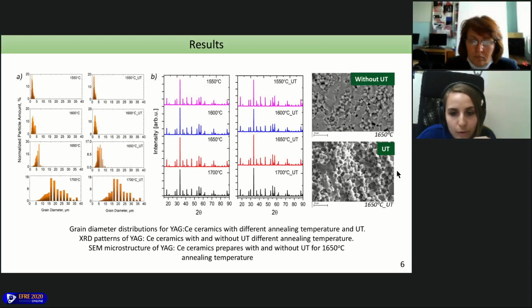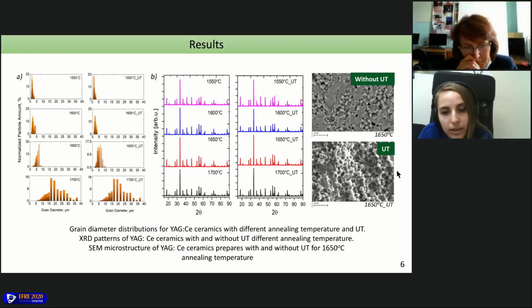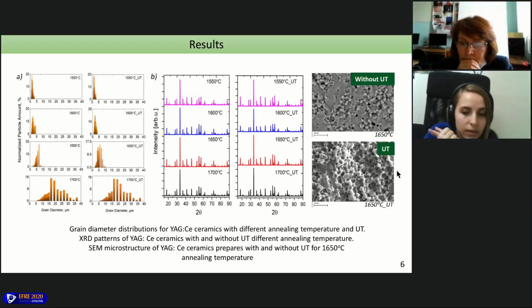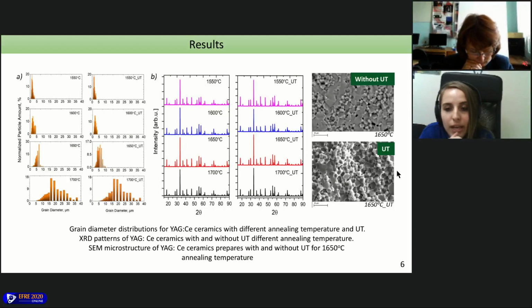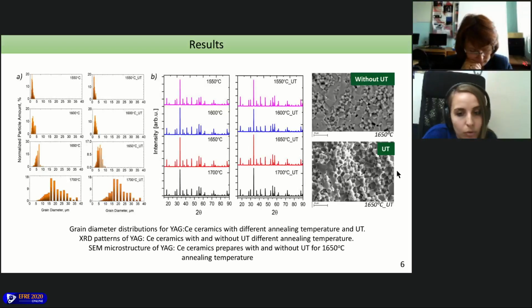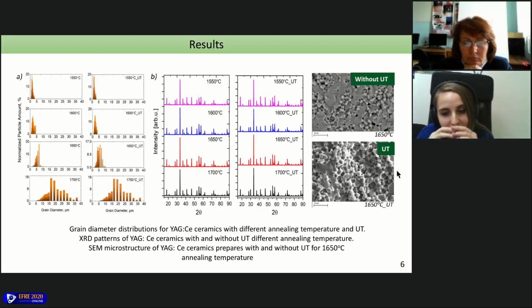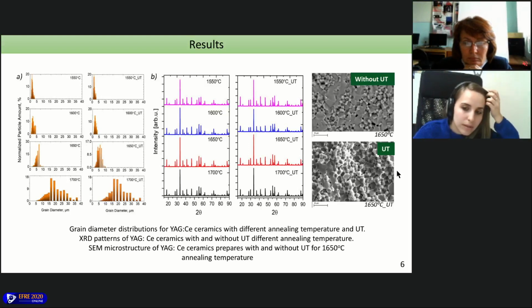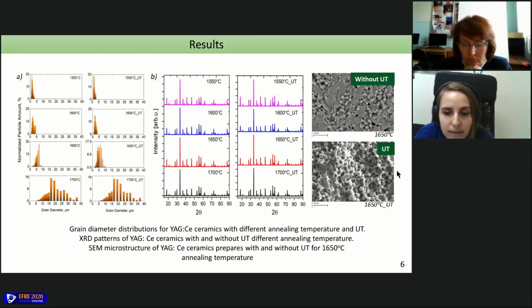And so the consolidation of the sintered material is very intensive, accompanied by a decrease in the number of pores and grain growth at the temperature of 1650 degrees. And the compaction process of the sintered YAG with cerium ceramics slowed down dramatically at the temperature of 1700 degrees, and this signified grain growth, leading to the transfer of intergranular residual pores into the grain volume.